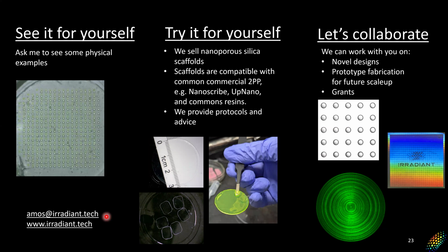And can the materials withstand repeated cycling? That's the real problem with the ultra cold stuff. Yeah, I think so. We have not done rigorous testing on that, but we have taken these and dunked them into liquid nitrogen, taken them out, and they work just fine. But I don't have much more rigorous testing than that at this point. A lot of the IR optics I've played with have trouble with repeated cycles between liquid nitrogen, 77K, and room temperature for a few hundred cycles. Once you do that testing, I expect it will be good, because one of the nice things about having everything fully integrated in this structure is that it has some flexibility to expand and contract without falling apart, but everything is still tightly held, with nanometer precision, to where it is.